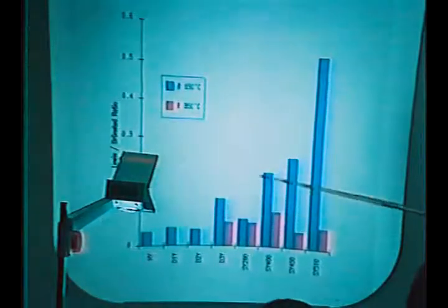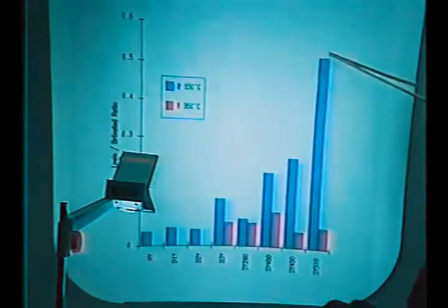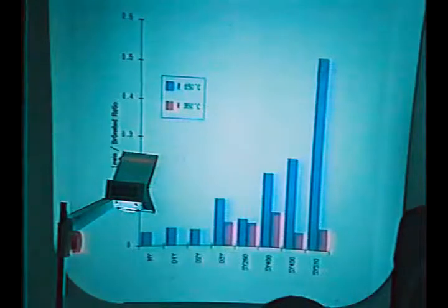all the weak and strong acid sites, you see a definite correlation: as you dealuminate these materials and go through more severe steaming, the Lewis to Bronsted ratio goes up. But when you go to 350, there is really no significant amount of Lewis acidity left. So this points, in our opinion, to an inductive type of effect, that Lewis sites are inducing strength into their neighboring Bronsted sites rather than directly participating in the reaction itself.